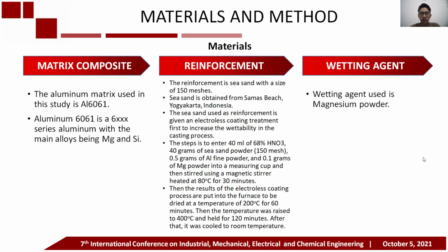In Chapter 2, I will talk about materials and method. The matrix used in the study is Al6061 with the main alloys being Mg and Si. For the reinforcement, we use sea sand, which is treated with an electroless coating. The steps of the electroless coating process are: add 40 ml of HNO3, 40 grams of sea sand powder, 0.5 grams of Al fine powder, and 0.1 grams of Mg powder into a measuring cup, then stirred using a magnetic stirrer, and then heated at 80 degrees Celsius for 30 minutes.